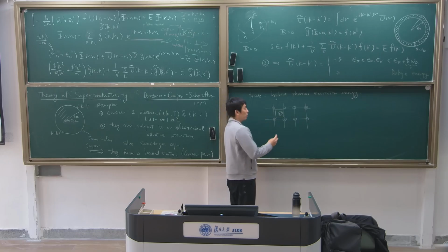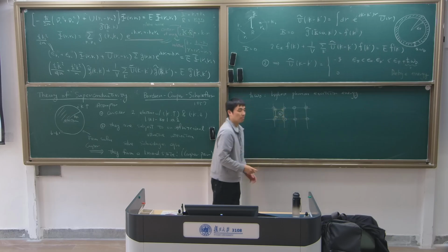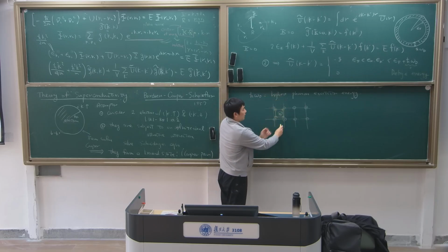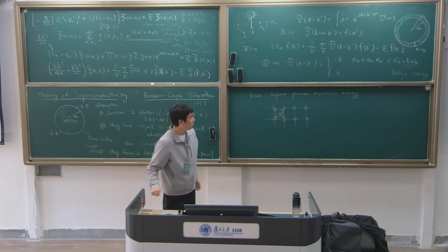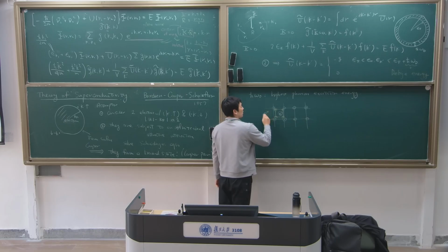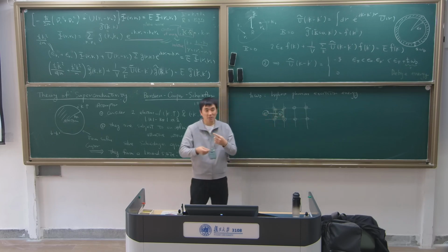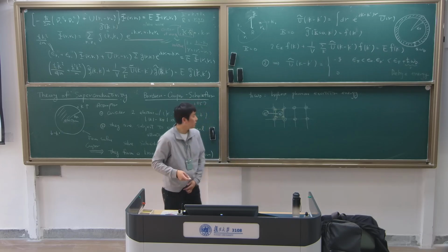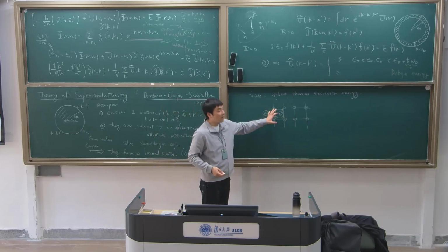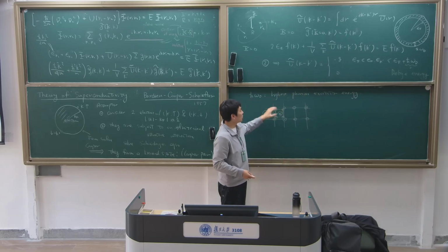This lattice is attracted by charge attraction, electric attraction, and this lattice becomes a bit small, and the net charge around here becomes positive. Therefore, another electron wants to come here, attracted by the net positive charge in this lattice. That's what I explained, I showed in a video in the first lecture. If you want, I can show you that later. And that will in fact create this attraction. And this attraction is called phonon-mediated.